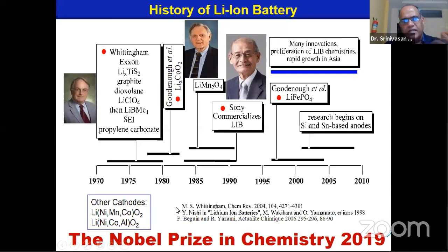Later, many other advanced battery technologies were developed using various other materials, such as lithium nickel manganese cobalt oxide, called NMC, as well as nickel cobalt aluminum oxide, called NCA. With this combination, Tesla batteries and others are using NCA as the cathode and graphite with silicon as the anode material, which gives high energy density. Because of this invention, the lithium-ion battery is now available in the commercial market for various applications. Recognizing their effort, all three gentlemen were awarded the Nobel Prize in Chemistry in 2019.